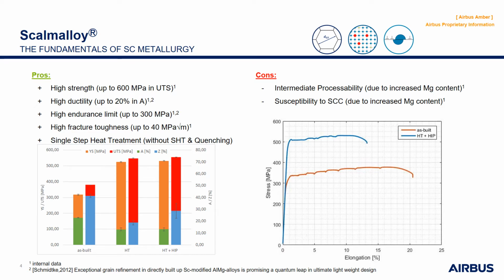But we also face some issues with this alloy, especially when processing high magnesium variants. Due to the high magnesium content, we only see an intermediate processability, especially when process parameters are not perfectly adjusted. We also face a susceptibility to stress corrosion cracking. So actually, it's all about magnesium, which seems to be the bad player in this game.